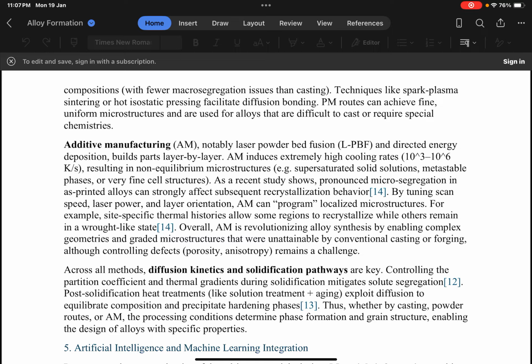in non-equilibrium microstructure. For example, supersaturated solid solution, metastable phases, or very fine cell structures. As a recent study shows, pronounced microsegregation in as-printed alloys can strongly affect subsequent recrystallization behavior. By tuning scan speed, laser power, and layer orientation, AM can program localized microstructure. For example, site-specific thermal histories allow some regions to recrystallize while others remain in a wrought-like state.